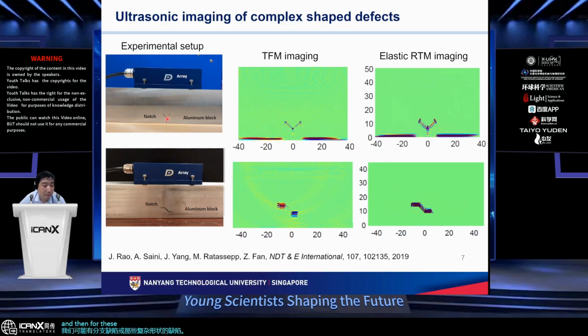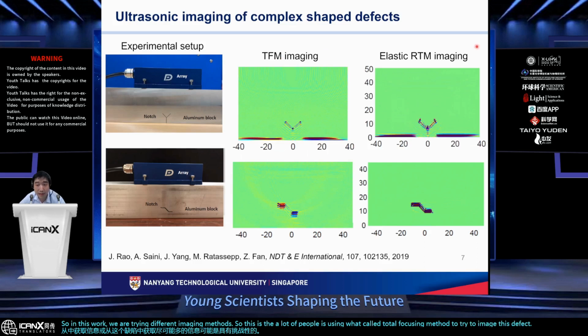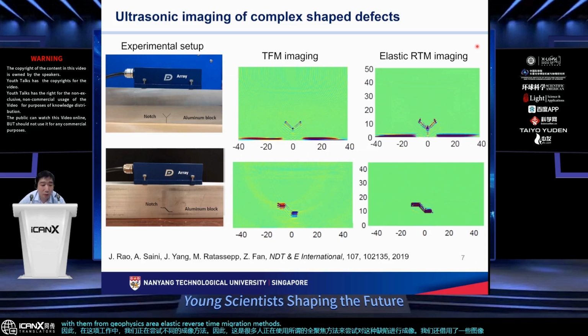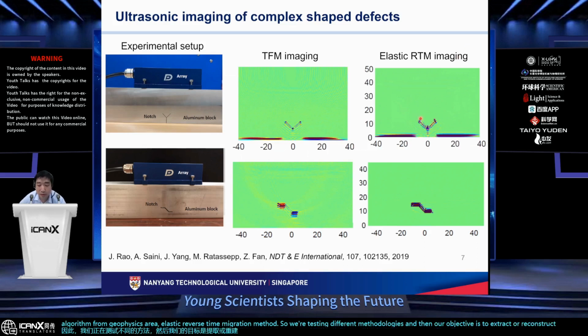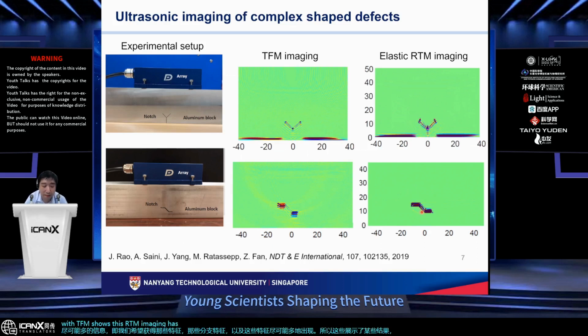And for these complex defects, getting as much information as possible from the defect could be challenging. So in this work, we are trying different imaging methods. A lot of people use what we call the total focusing method to try to image this defect. And we also borrow an image algorithm from the geophysics area, the elastic reverse time migration method. So we're testing different methodologies, and our objective is to extract or reconstruct as much information as possible, i.e. we want those branch features, and also these features, to appear as much as possible. So this showcases certain results. The comparison with TFM shows this RTM imaging has a certain advantage.